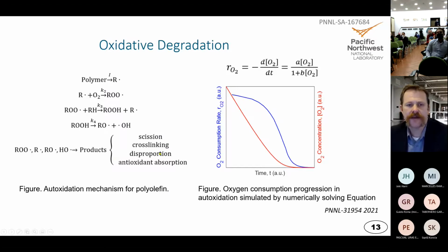In thermal and radiation aging as well, for these polymers, the major mechanism of degradation is oxidative degradation, where the polymers, the hydrocarbons, are reacting with oxygen in the atmosphere, and reactive radicals get generated in the polymer from the radiation or from the heat, and those react to break up the polymers and change the mechanical properties. The major concern is that they embrittle the polymer, and then if there's an accident in the plant, they won't perform their function. So the oxygen gets consumed in that reaction.